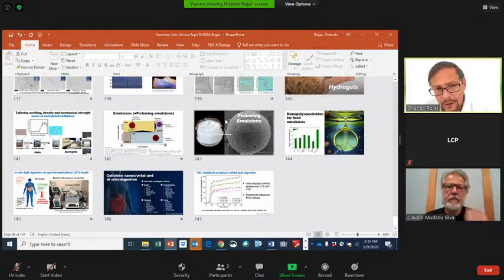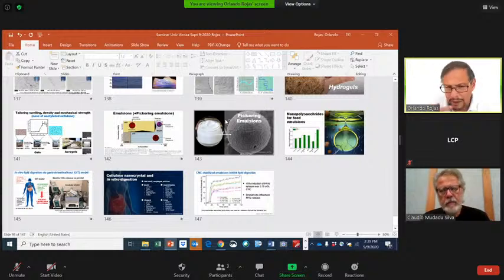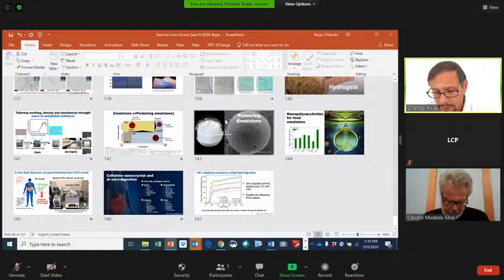For CNF, of course, the yield is very high because what you do is mechanical deconstruction. So once you start with fibers, the yield is pretty high for CNF. And for bacterial cellulose, maybe it's difficult to talk about yield unless you think about the yield in sugar conversion from the culture medium to the nanocellulose, right? And there we have different yields depending on the microorganism.